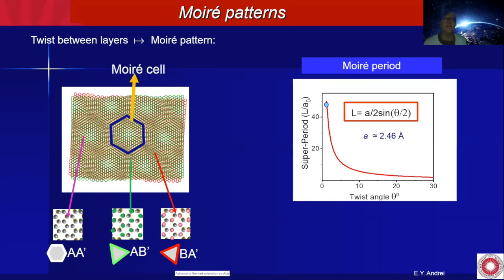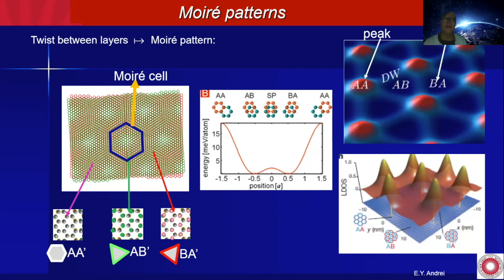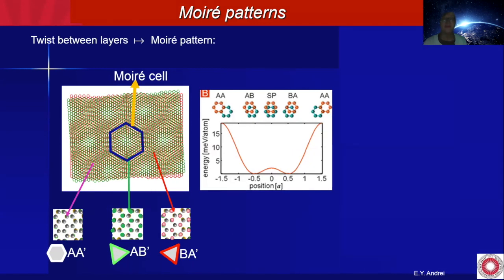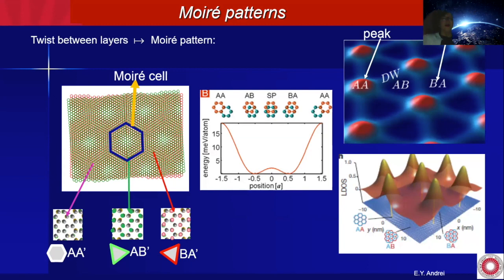However, this Moiré pattern does something more than just this pretty interference pattern. If you calculate the energy to have an AA stacking, you see that it is vastly larger than the energy to have an AB stacking. As a result, this Moiré pattern induces a modulation in the spacing between the two layers, which is about a 10% modulation. So you have peaks and valleys alternating that follow the pattern of the Moiré cell. One of the consequences in terms of the density of states is that the electrons will love to pile up in the AA region. So you have a large density of states in the AA region that alternates with small densities of states in the valley regions, in the AB regions.